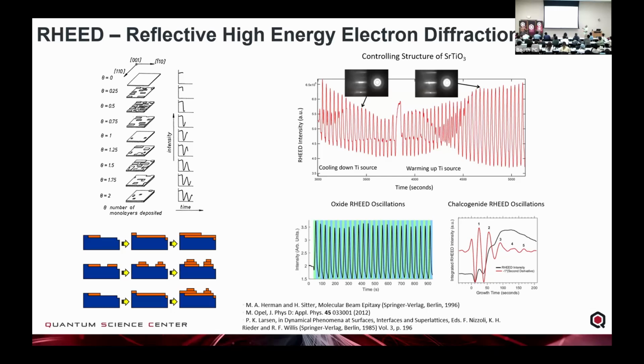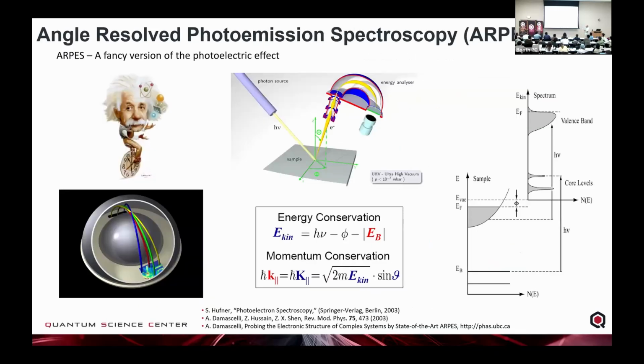And here, this is the growth of strontium titanate, where we're actually controlling the individual sources of the material, and we can control the structure and get the structure to flip while it's growing. And so now we can find ways to control the symmetry, control the properties of the materials as it's growing. So that gives you a sense of how we actually make the materials using molecular beam epitaxy. So how do we look at the electronic structure?